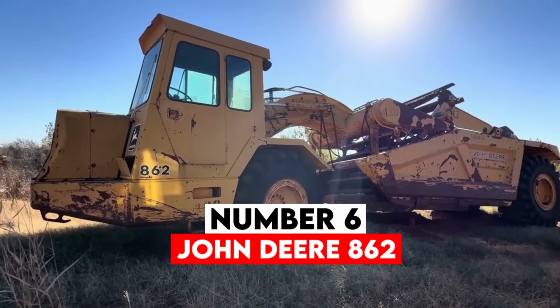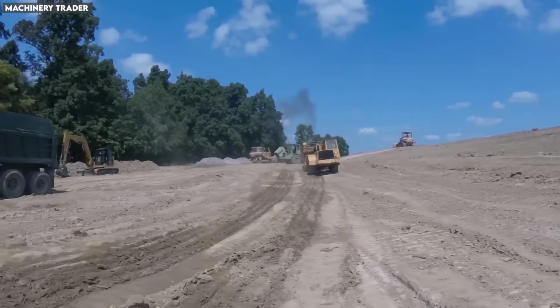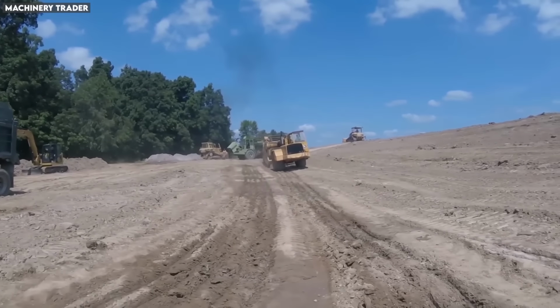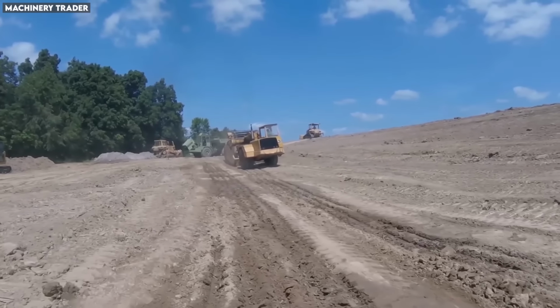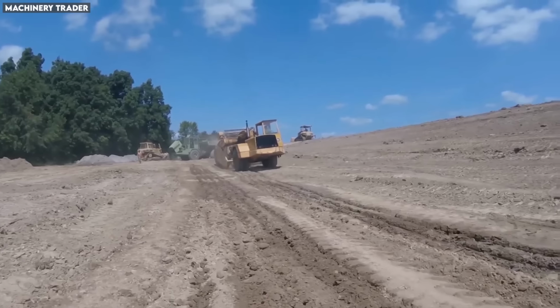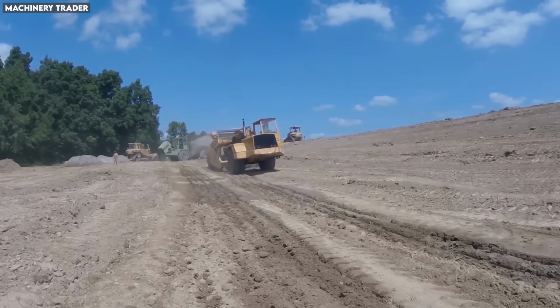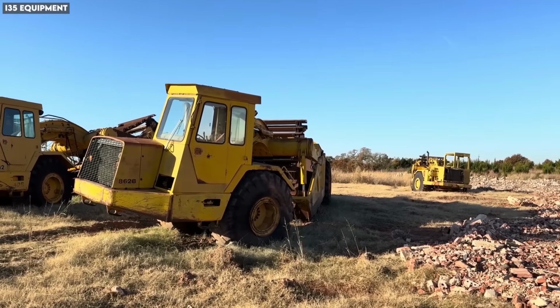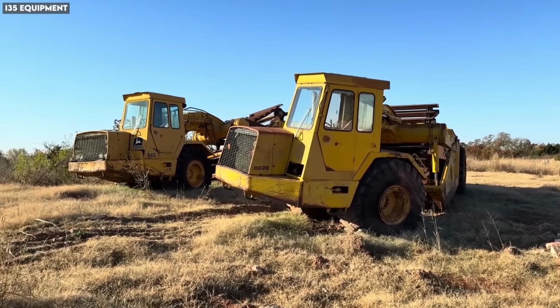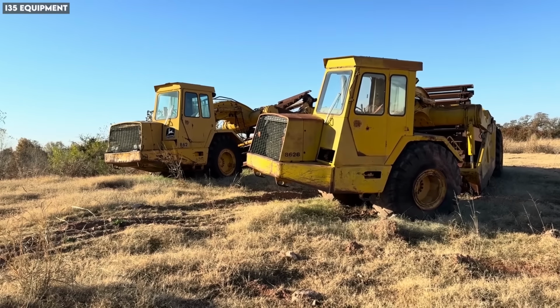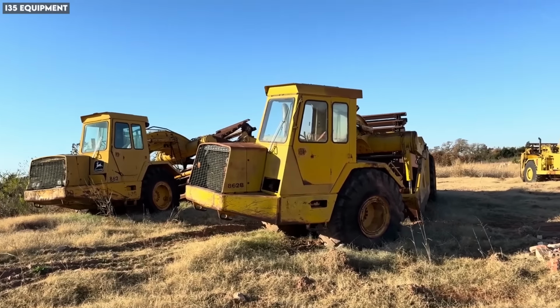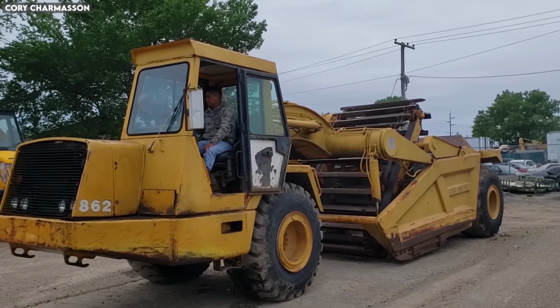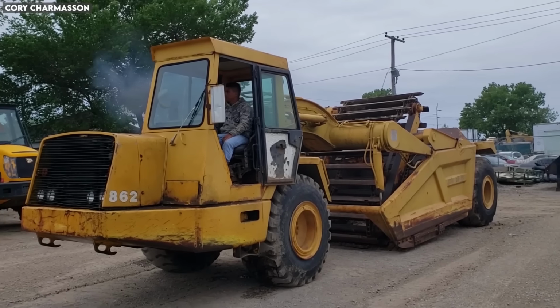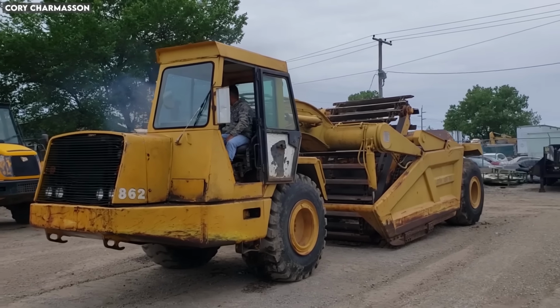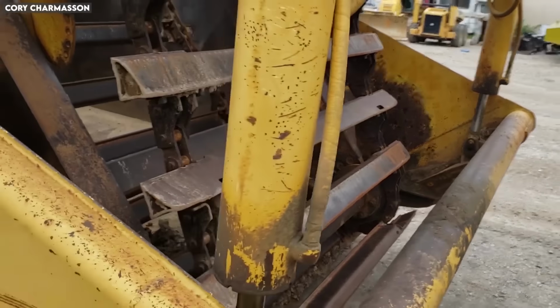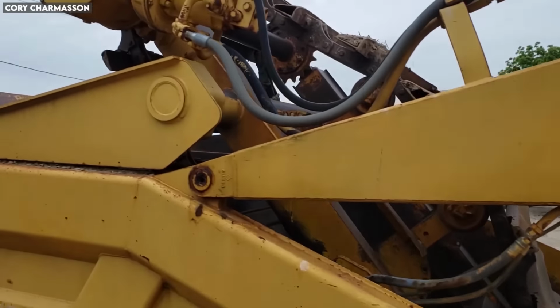Number 6. John Deere. The 862. Deere's entry into the large scraper market brought agricultural equipment reliability standards to heavy construction. The 862 featured a 32 cubic yard bowl with what Deere called their Dura-Bowl construction. The bowl was fabricated from overlapping plates with welded joints ground flush and then heat-treated. This process created a bowl with no stress risers or weak points. The heat treatment also work-hardened the steel, effectively increasing its hardness by 60 Brinell points without making it brittle.